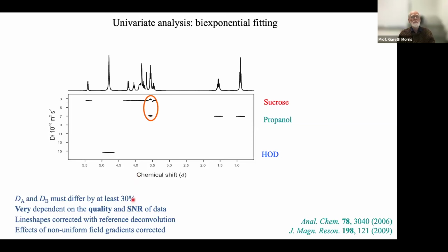Now, the other really frightening thing is that if you do a bi-exponential fit on the raw data here, you actually see two diffusion coefficients for every single signal. It looks as if the whole spectrum has been doubled. And the reason for that is that it's very difficult to make a pulsed field gradient coil that simultaneously has good dynamic and good static properties. If you design your gradient coil to allow you to do very short clean gradient pulses, then the gradients will vary quite a lot with position. Correspondingly, if you can put up with fairly slow rise and fall times, then you can get a flatter distribution of gradient as a function of position.